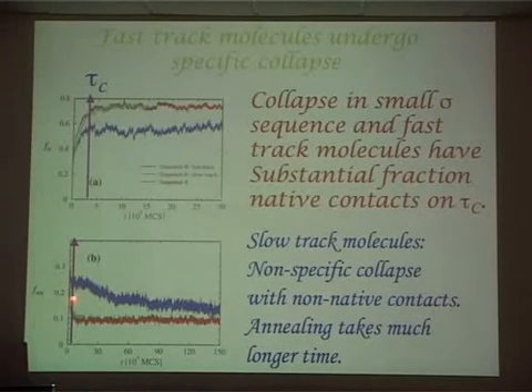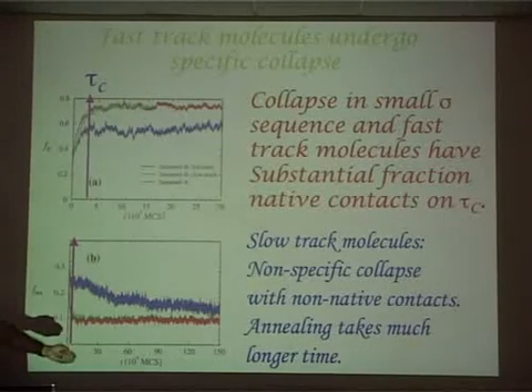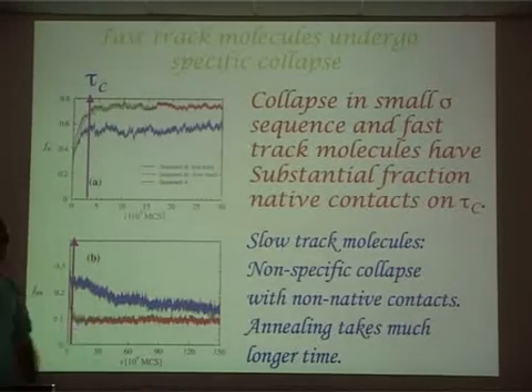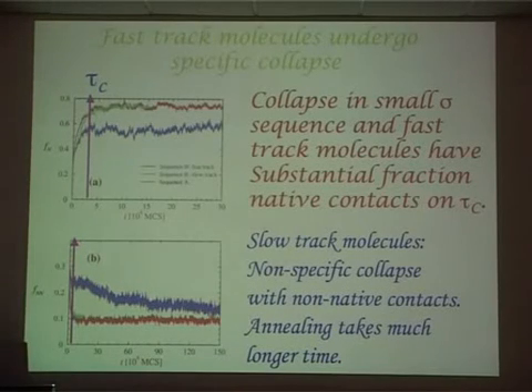Whereas, let's come back to the non-native interactions. When you look at the non-native interactions, how much non-native interaction is in the compact state, you see that there's very little, only 5%, 6% or something like that, in both the fast track molecules and the sequence A, whereas there are lots of incorrect interactions in the slow track molecules in the competing basin of attraction that had to be undone to fold. So collapse itself is different in these two sequences.